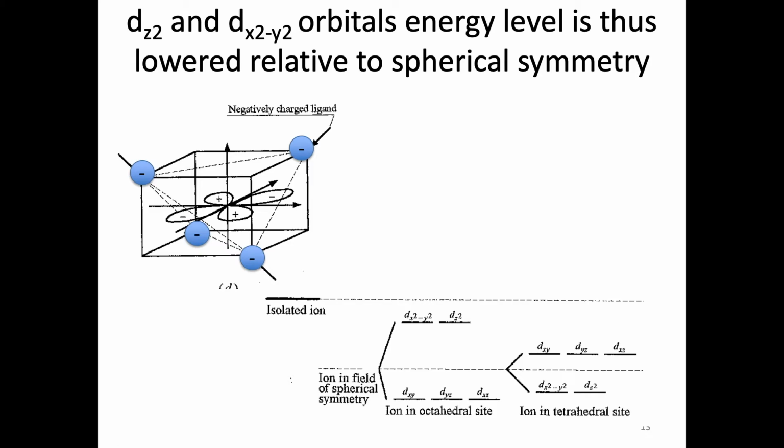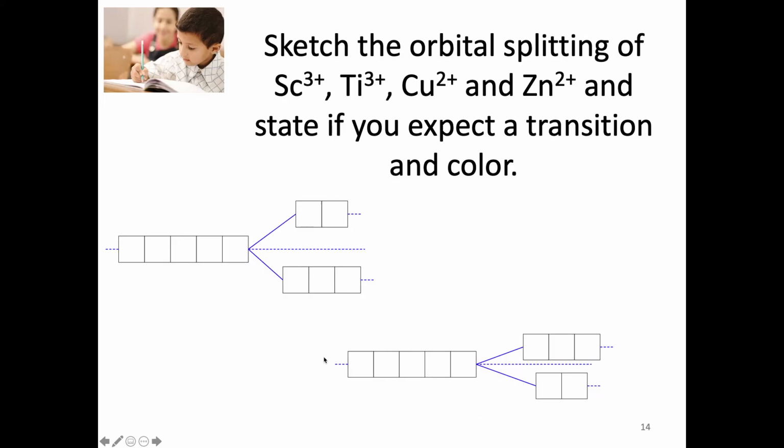So we're sort of illustrating the why we see the splitting in the specific way that we do, because the ones that are at the higher energy state are repulsed because they are in closer spatial relationship to each other, whereas the other ones are not as close, and so they get pushed to a lower energy state, with the sum of that equaling what's in the spherical symmetry.